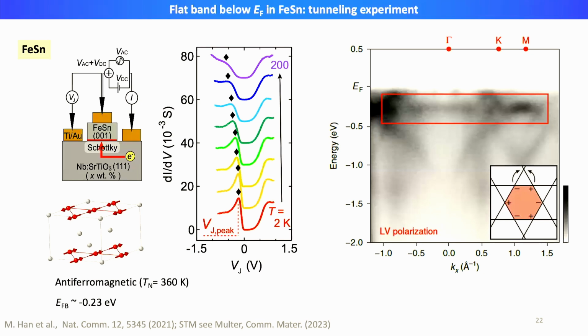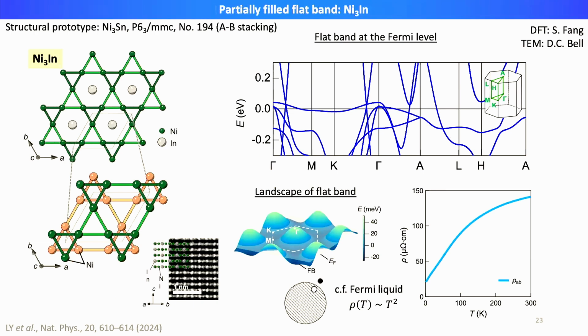So up to now, we've established the presence of this flat band somewhere in our electronic structure, but I haven't shown you what kind of consequences they can induce. More recently, we were finally able to bring the Fermi level into the flat band, and this is the material where we've managed to achieve this. The material has the composition nickel three indium, and it still has kagome layers of nickel that are AB stacked right upon each other. You can also see this stacking sequence from the transmission electron microscopy cross section of these crystals.